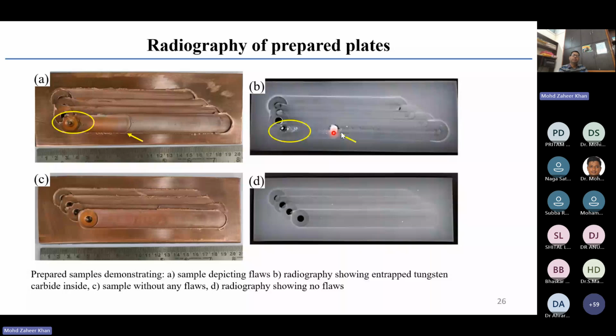Similarly, the debris of the tool, that is the tungsten carbide tool, which was chosen for this experiment, is also stuck up, and is also causing problems. The other radiograph, you can see this is not having any flaw, this is not having any defect, but as you can see over here, the offset distance was slightly more, so there is an unbonded region between the two passes. So in this way, we could optimize the offset distance, and we could produce the friction stir welding passes.